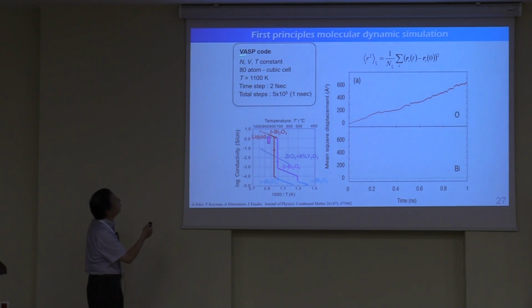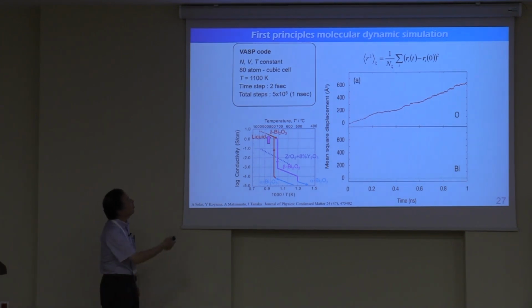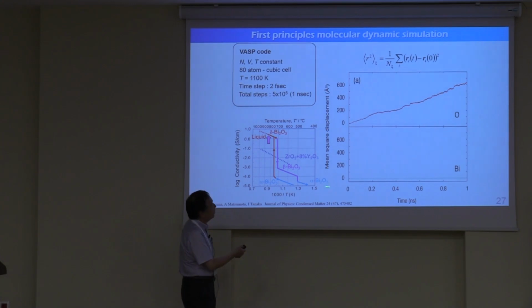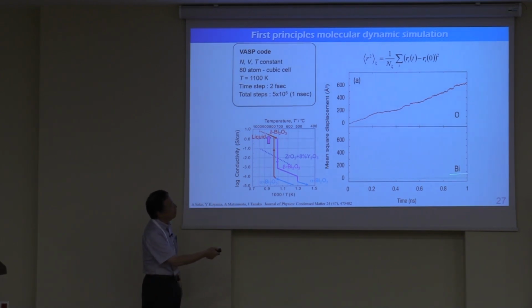What we have done is a first-principles molecular dynamics calculation using the NVT constant ensemble and an 80-atom cubic cell at this temperature. The time step was 2 femtoseconds. Femto, pico, nano differ by three orders of magnitude. We performed the 2-femtosecond steps up to 1 nanosecond. So this is the mean square displacement from first-principles molecular dynamics calculation for bismuth and oxygen.